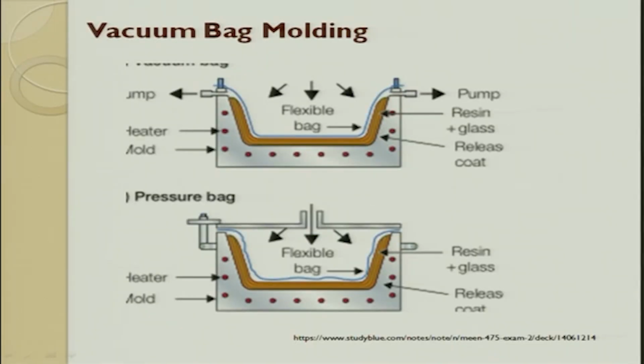So, you can see here, this is a flexible bag. I gave you an example of a boat. If you want, you can have it. Here the prepreg or the hand layup process is completely placed, glass fiber is done. Below this you have a release agent coating. You can apply heat for curing, and here is a pump which is used for sucking and creating vacuum, and you apply a flexible bag, there also you apply pressure, so that you get a good output. The pressure bags are also there. You put it on top of the pressure bag.